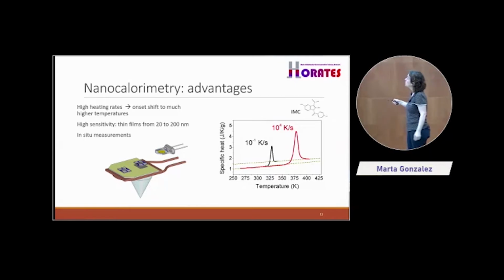So we put our chips inside our deposition chamber, we prepare our samples, we measure them. This is an advantage because they are in situ measurements. We don't need to take our sensors out, do the measurement, clean them, and then start again. In fact, if we are working with organic systems, if we heat it enough, it evaporates in the vacuum chamber, so we can use the same chip many times. It's very sensitive, as I told you, and we have high heating rates.